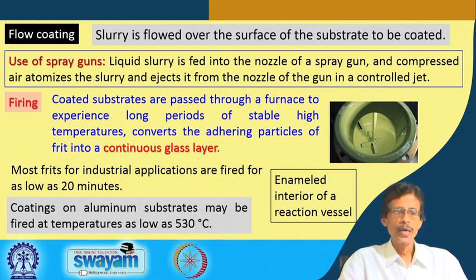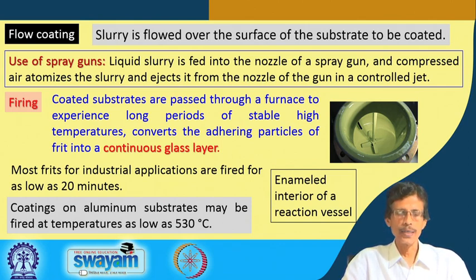So, if you have an aluminum substrate material in your hand, a temperature of 530 degrees is fine, is sufficient, and you can have 20 minutes or more of residence time of that particular frit material during the firing process. That will give you the typical covering of the enamel material on the aluminum surface.